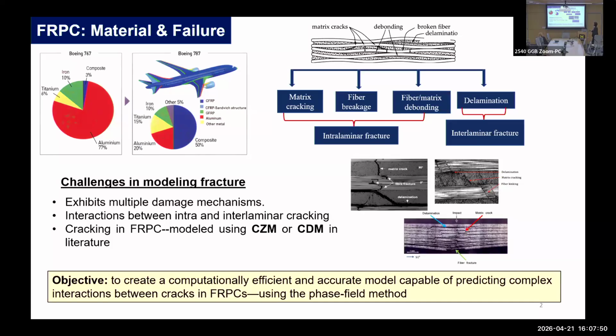Now, each of these methods has their own advantages and disadvantages. For example, cohesive zone modeling requires the description of the cohesive zone a priori to the propagating crack path. So if we know the crack path beforehand, then we can define the cohesive zone along those paths. But if we do not know a priori which way the crack will propagate, then it demands that we prescribe the cohesive zone model for the entire domain and becomes quite extensive computationally. So our objective in this project was to develop a computationally efficient and accurate model that is capable of all these complex features describing the fracture behavior of fiber-reinforced composites.